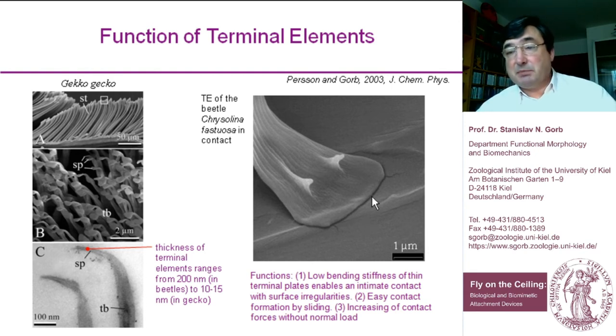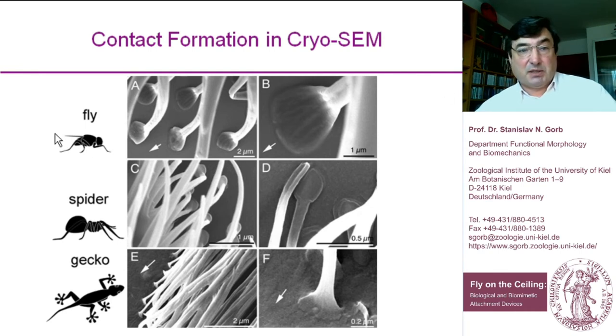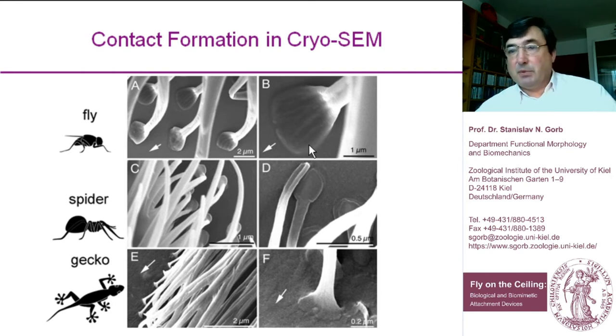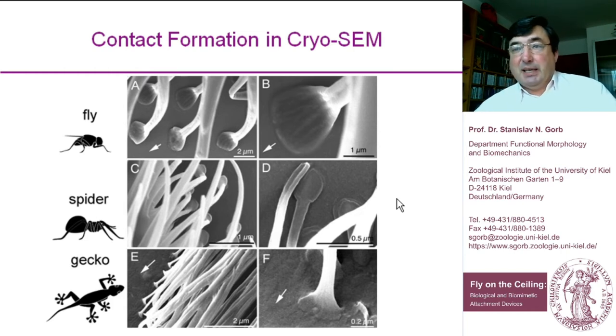If we study fresh contacts of flies, spiders, and geckos using cryo-SEM, we see something in common: all these animals generate contact with a plate-like spatula structure. From an evolutionary point of view, these animals have nothing to do with each other, but this convergence is strong evidence that this is a good design principle — and that information is worth providing to engineers, because if we want to walk on the ceiling one day, we may have to do something similar.